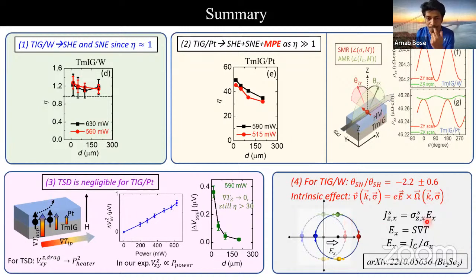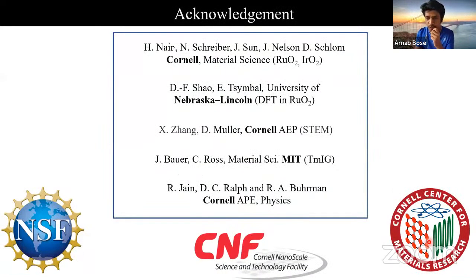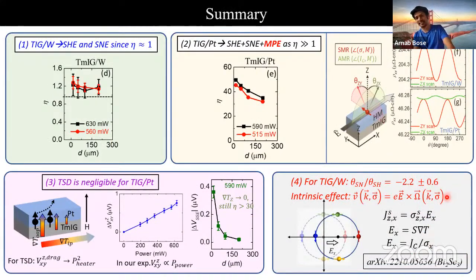This also suggests that we can have a material where the spin Hall effect is large, and we can also get large Seebeck coefficients, such as bismuth selenide. In that system, we can also get very large transverse spin current, as reported in our recent arXiv paper. For more details, you can refer to this work.